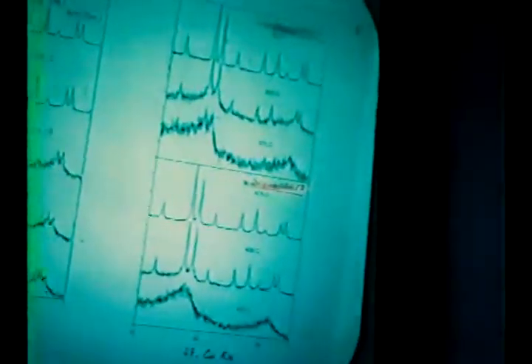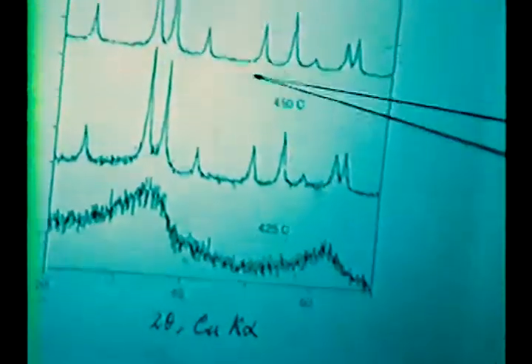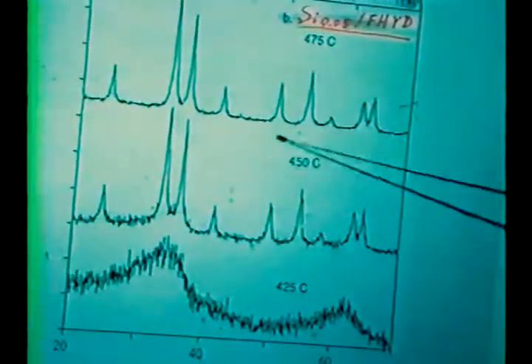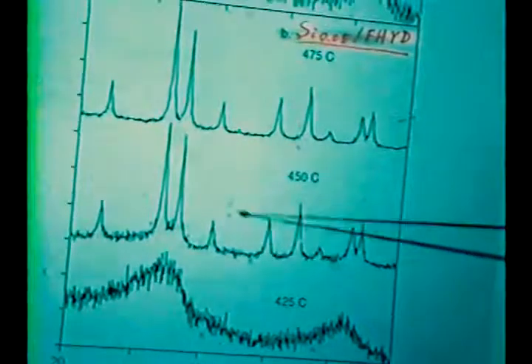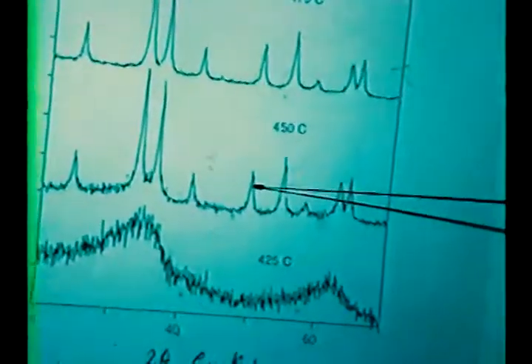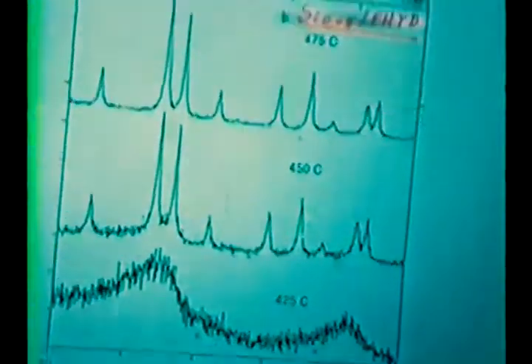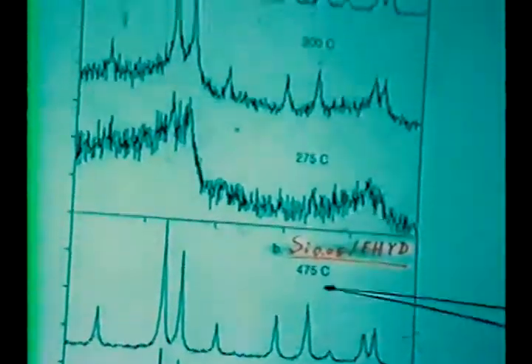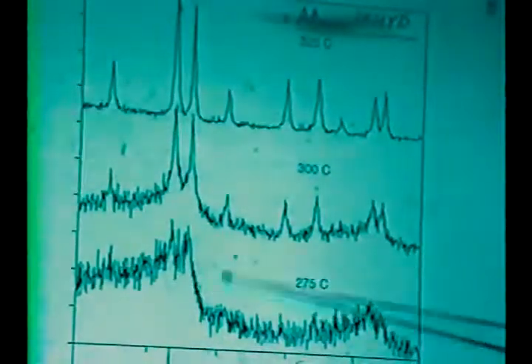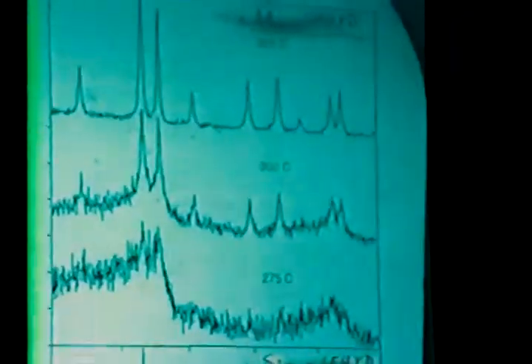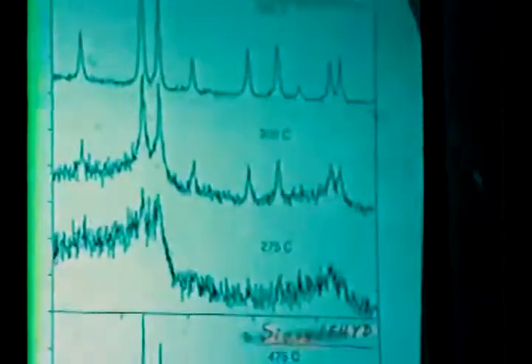Now if I add silica or aluminum to the precipitation solution: with silica at 425 C, you don't see any phase change, and increasing the temperature to 450 C you see the formation of hematite. Alumina is not as good as silica, but still the transition temperature increased from 225 C to 275 C.